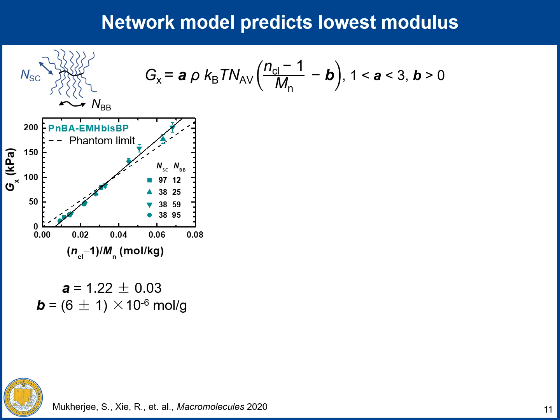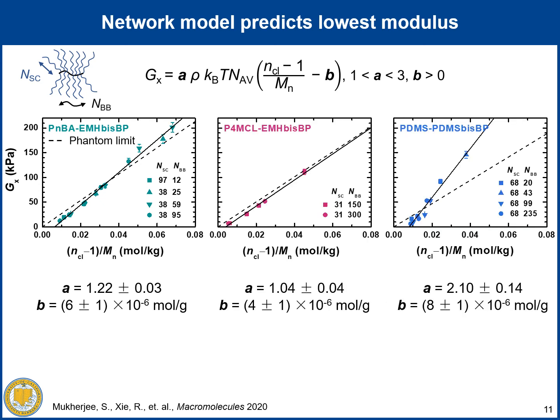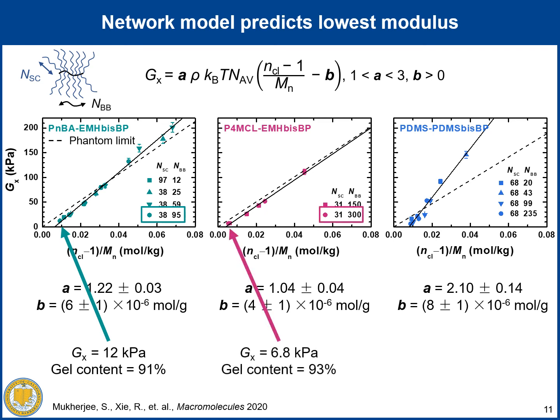And we can apply the same study to the other systems with different side chain chemistry, and all of the fitted parameters do fall within the expected limits. The main power of this model is to predict the softest moduli possible for a given Bottlebrush polymer. And indeed, we have achieved super soft moduli around 10 kilopascal without sacrificing the gel content. And we can repeat this process for other Bottlebrush polymers with different side chain chemistry as well.